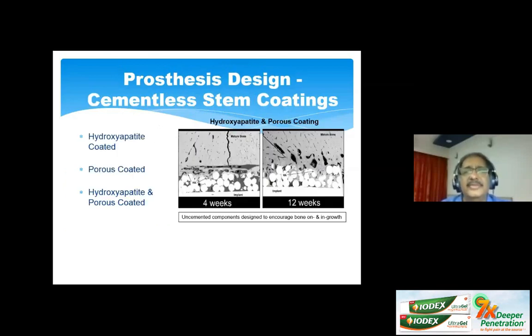This is a similar picture to what we said, whether they are hydroxyapatite or porous coated, or could be a combination of the coating. They are designed to encourage bone on-growth and ingrowth, and at 12 weeks, histological pictures show very successful ingrowth into the parent bone.